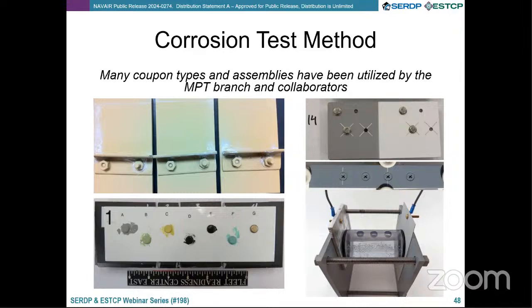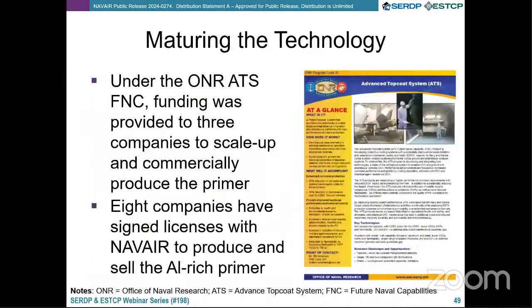And so a lot of our more specialized materials, as you see on the bottom left, those are mock-ups of actual aircraft parts that have been cut out of a plane. And so you can go to perfectly fabricated assemblies that are the exact matches of materials you would find on aircraft, or you can go to test using very simplified off-the-shelf parts and hardware. And I think we pretty much did everything in between before we convinced ourselves that a simplified test is still acceptable.